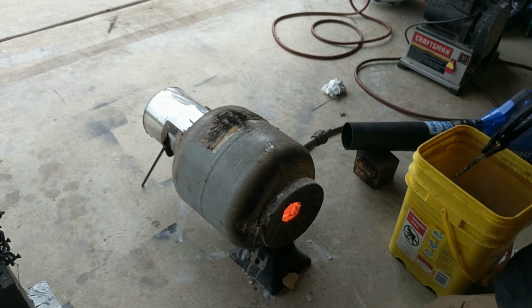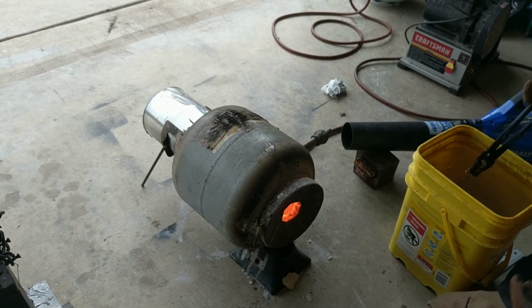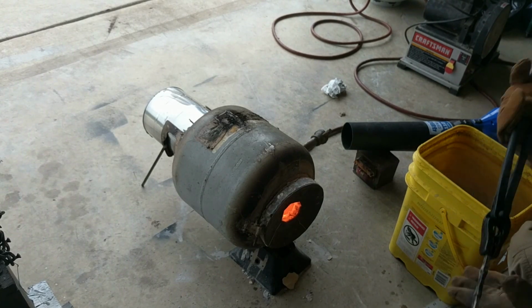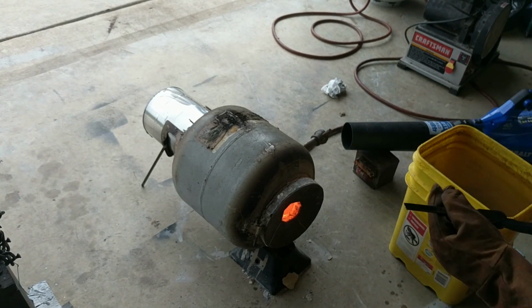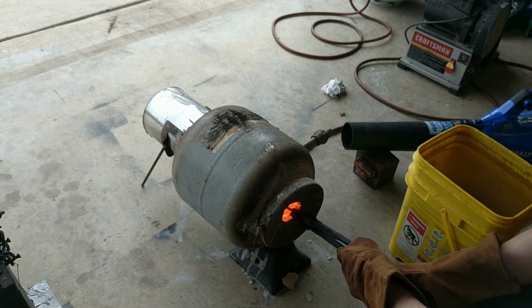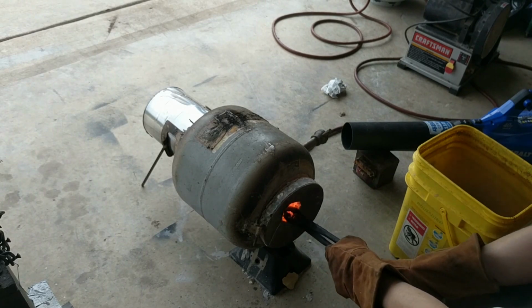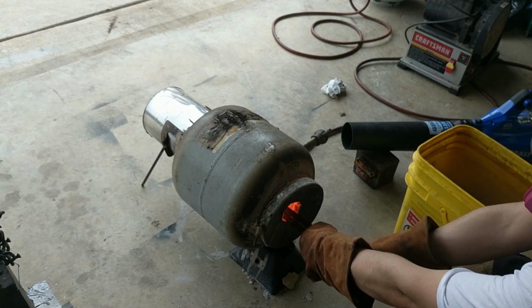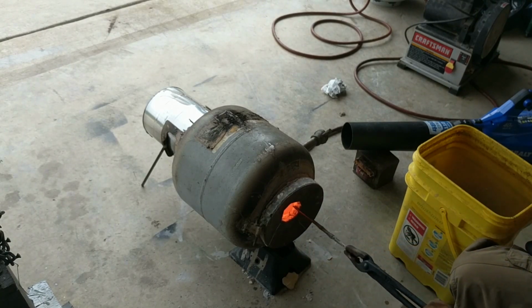The internal stresses at this moment are staggering, and a decent portion of blades do not survive, cracking or snapping in half outright. Luckily, it does not seem to be the case this time. The blade is immediately returned to the forge for just a moment to heat it up to about 400 Fahrenheit, thereabouts, to take some of the stresses right out of the steel.